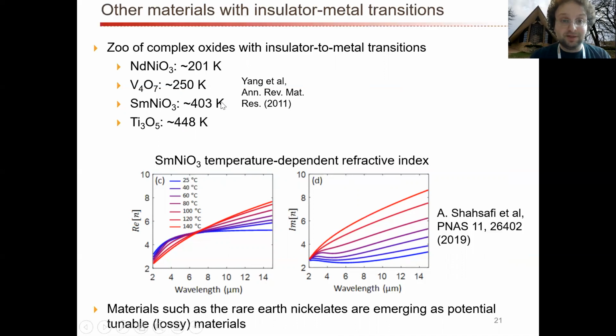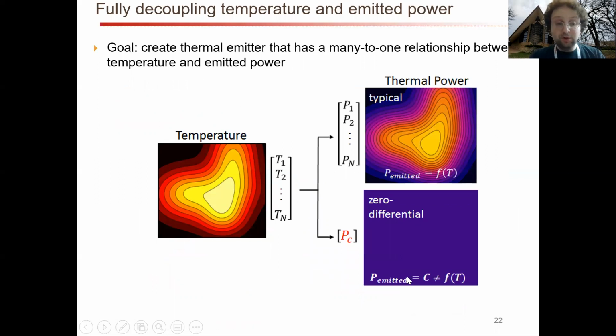But we decided to take a look at this samarium nickel oxide, and we did this spectroscopic ellipsometry, now just in the mid-infrared, from 2 to 14 microns, observing this very large change in n and k, but it's quite gradual, which we thought was going to be kind of an interesting material system for us. And so the goal that we had initially using this material system was to create a thermal emitter that has a many-to-one relationship between temperature and emitted power. I mentioned at the very beginning of this talk that traditionally your temperature and power relationship is a one-to-one relationship. The hotter an object is, the more light it gives off, and that's why infrared cameras can see a lot of information about the temperature of the environment. We wanted to make a many-to-one relationship where no matter what temperature you were at, the camera read the same thing, and therefore it's a way of concealing information.